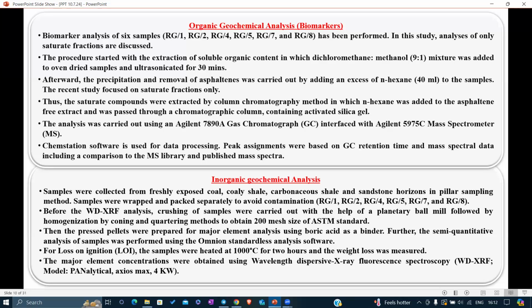We have considered these litho units. Before the XRF analysis, crushing of the samples was carried out with the help of a planetary ball mill, followed by homogenization by coning and quartering method to obtain 200 mesh of the ASTM standard. Then pressed pellets were prepared for the major element analysis using boric acid as a binder. Further, the semi-quantitative analysis of the samples was performed using Omnian standardless analysis software. For loss on ignition, the samples were heated at 1000 degrees Celsius for 2 hours, and the weight loss was measured.